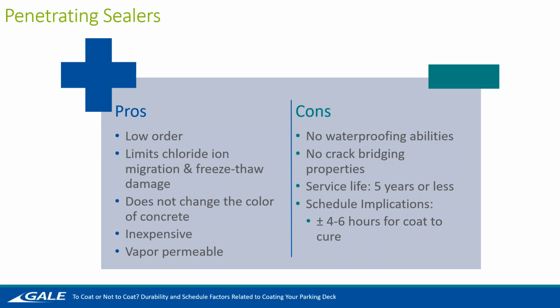Because of this cracking, because it's kind of rigid and it won't bridge those cracks, it needs to be switched out more often. And for schedule implications, it's about 4 to 6 hours for a coat to cure. So it's definitely one of our faster systems, almost comparable to the PMMA system that we have.